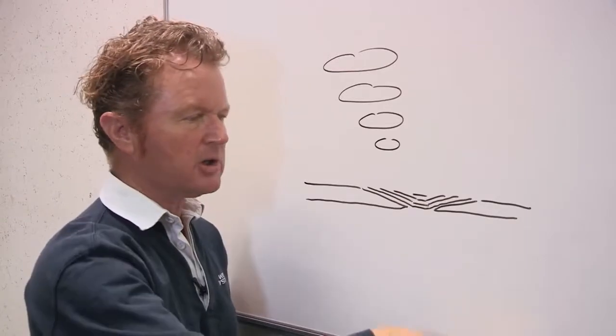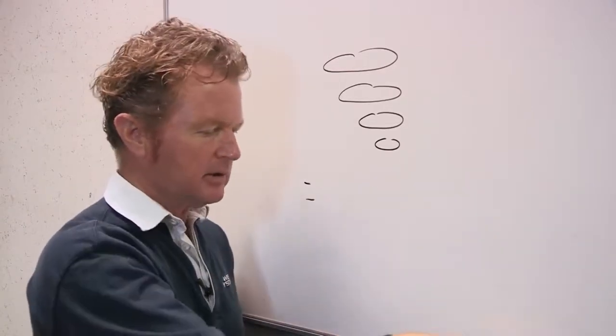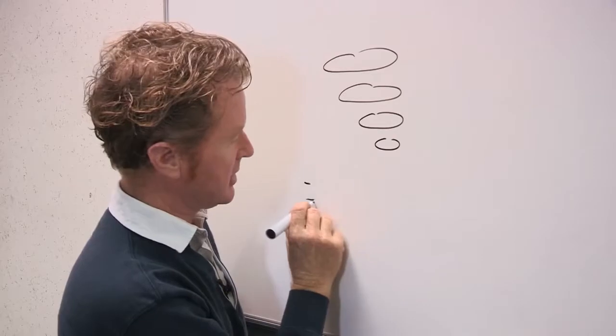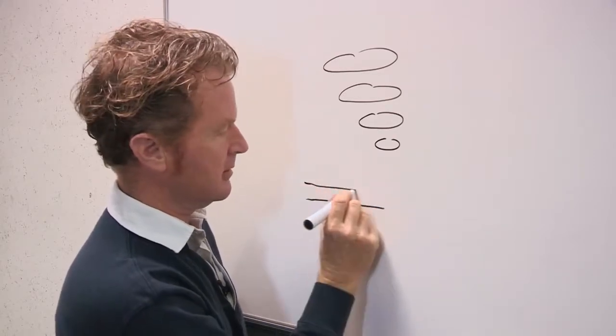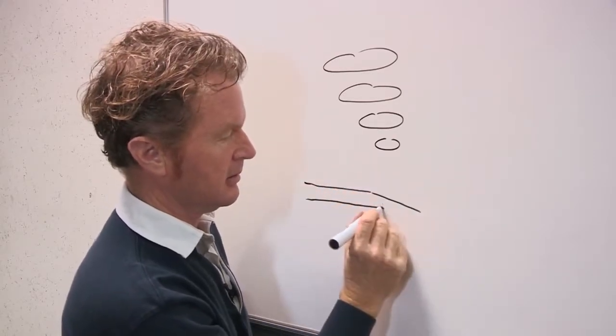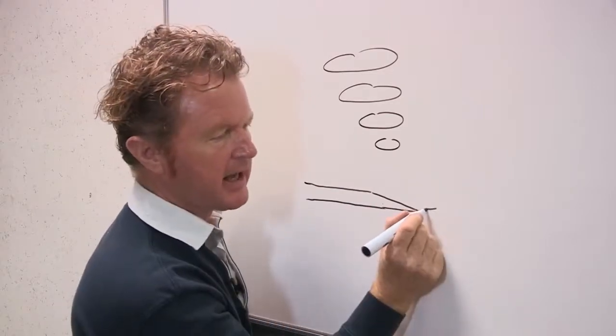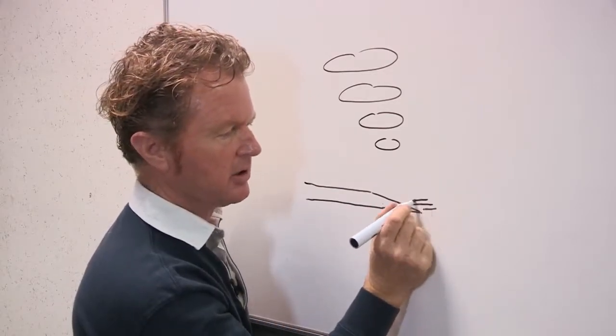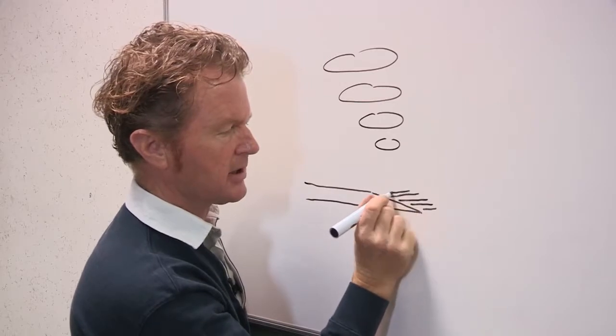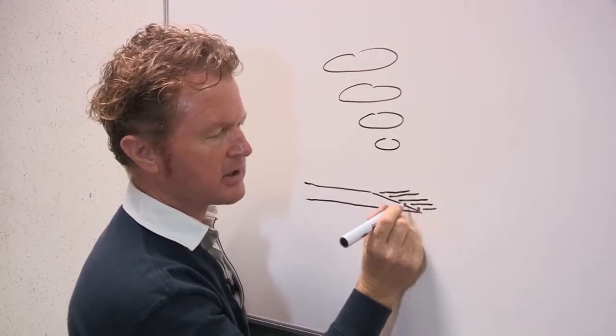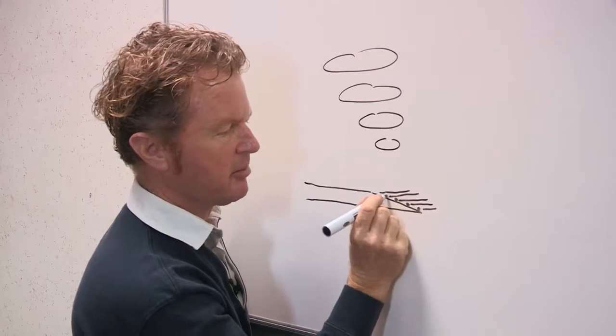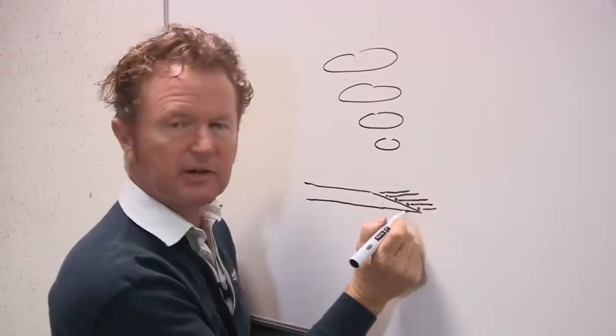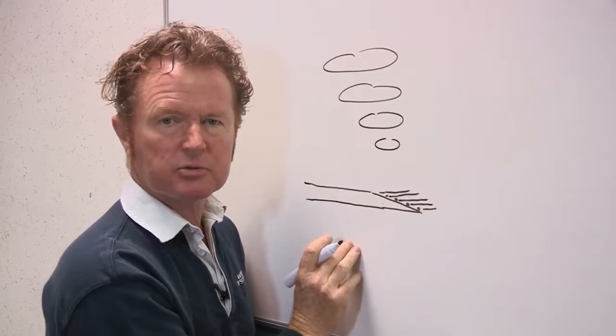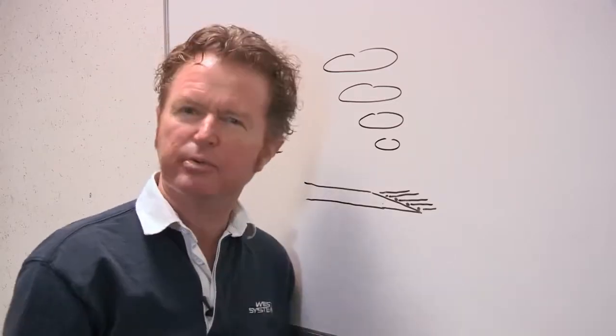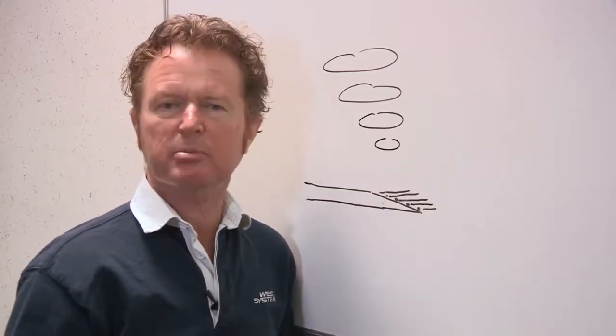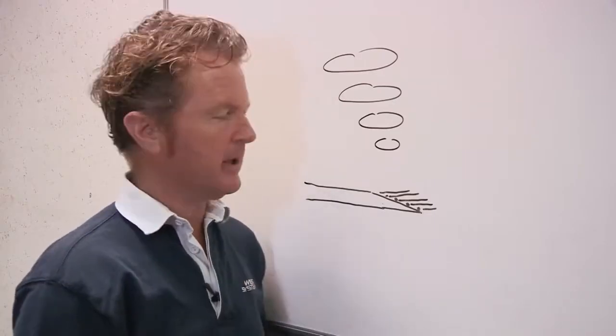Very important, because if you go with the smallest patch in first, you only ever get the edge of each individual patch contacting the surface. And what that does is it creates a series of air bubbles right at the interface of the bevel joint. And that does not produce a good repair. You want to produce best quality repair.